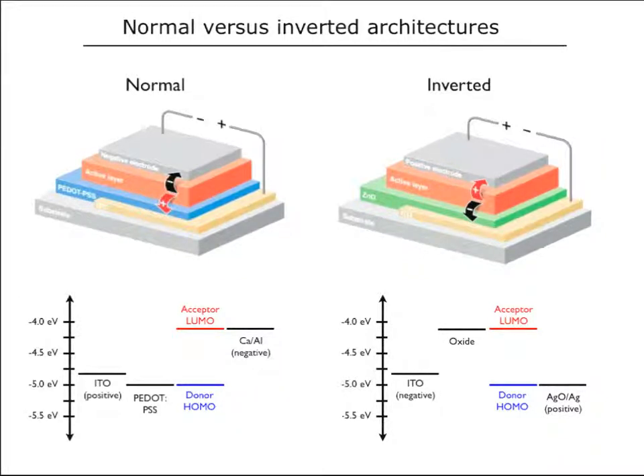So the devices themselves have two different geometries. We can make what would be called a normal device, where we have a low work function metal electrode, a negative electrode, and we sandwich the active layer between that and usually an ITO-based positive electrode. So we extract charges, negative charges from the top, positive charges from the bottom. We'll call that the normal device. We can invert the structure. So if we use a high work function top electrode, which can be gold or more commonly silver that we let oxidize a little bit, then we can extract the positive charges from the top. And what we do is insert an electron transport layer like zinc oxide, or can be TiO2, on top of the ITO to invert the direction of the device.